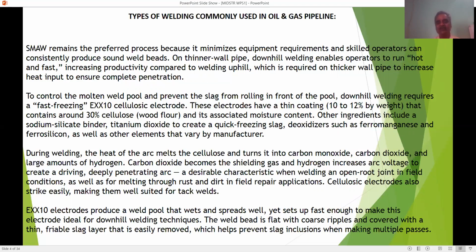On thinner wall pipe, downhill welding enables operators to run hot and fast, increasing productivity compared to welding uphill, which is required on thicker wall pipe to increase heat input to ensure complete penetration. To control the molten metal weld pool and prevent the slag from rolling in front of the pool, downhill welding requires a fast freezing electrode. Example, you can take 6010 electrode, a cellulose based electrode.